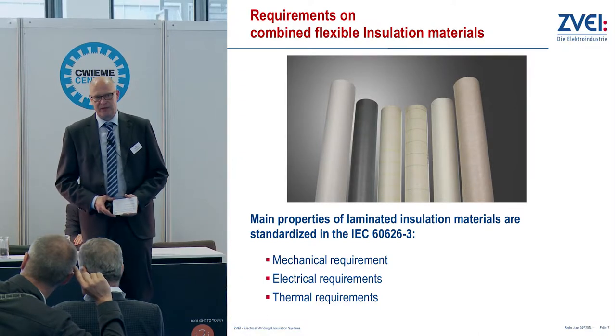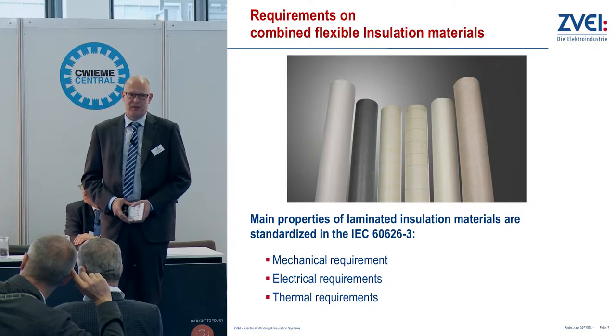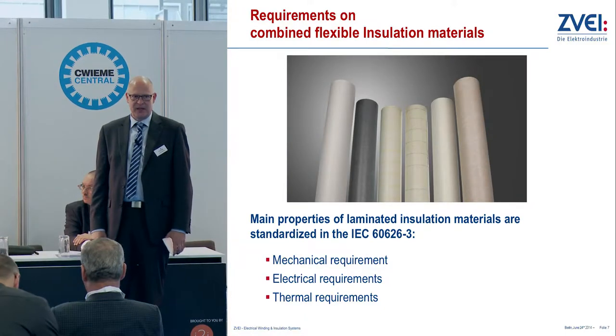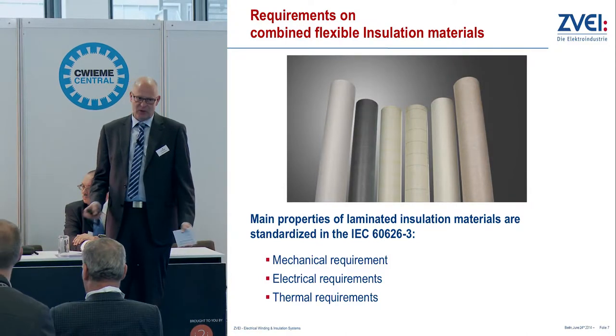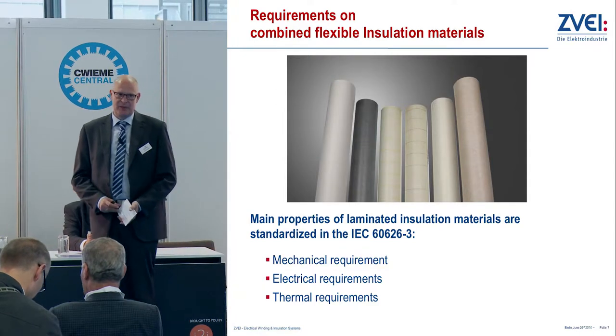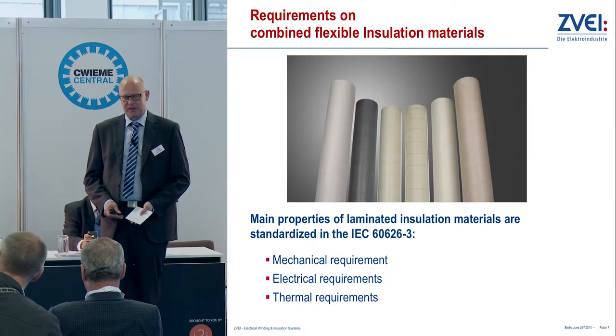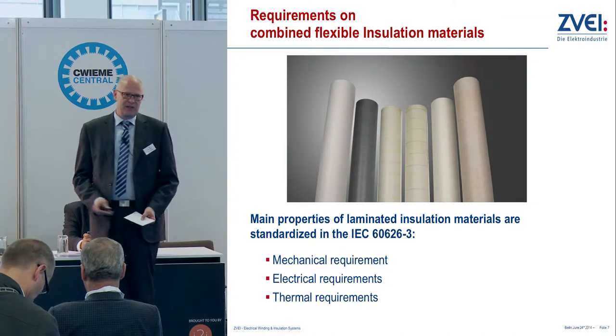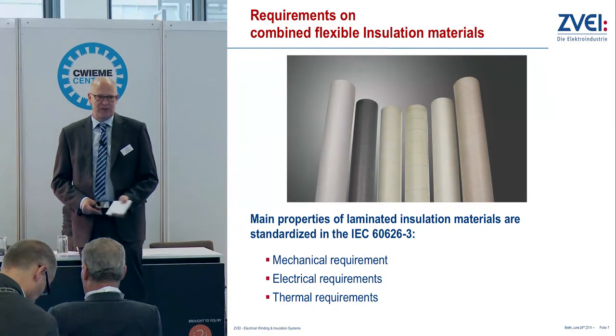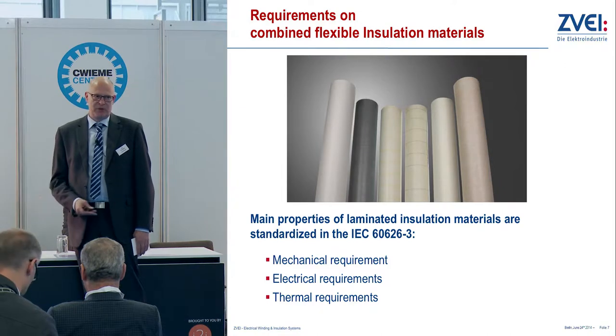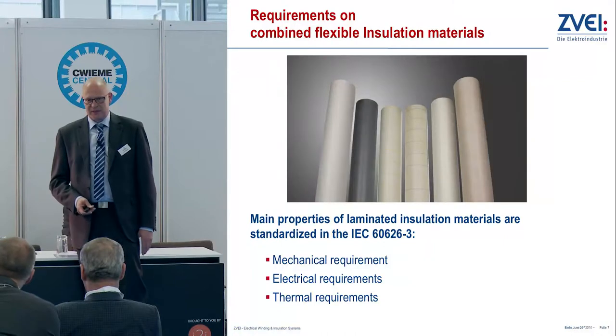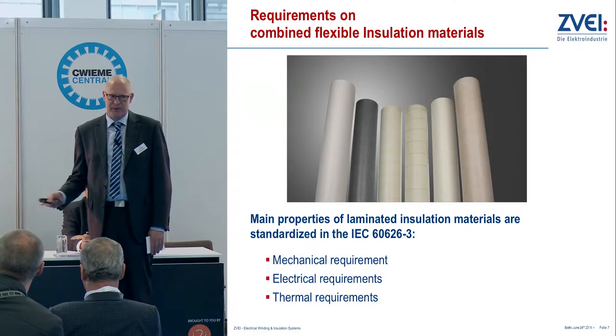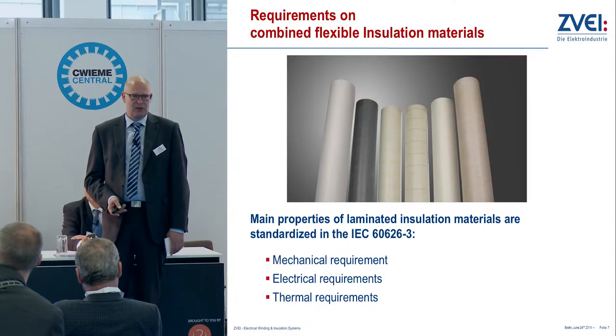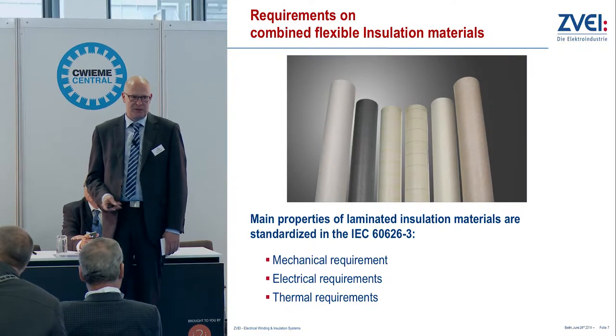Today, I would like to talk about the requirements on flexible insulating materials. The problem in this case is that most of our flexible insulating materials are already standardized in the IEC standard 60626. So I guess all of you are comparing the material with these standards. When we want to change to another insulating material, it will bring up some problems. But when discussing all the requirements from our customers, one big issue is always to increase the filling factor or to increase the converting speed of the insulating material. For the standard insulating material, we are limited due to the surface of Nomex, or for example, for DMD material, we are limited due to the coefficient of friction of the used impregnating resin.